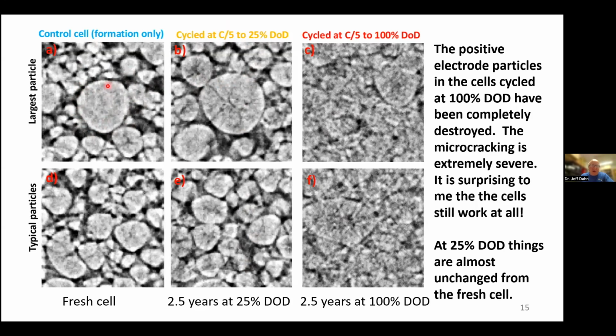We tried to find a large particle to compare. There might be some evidence of microcracking here, but very little. The image between the fresh cell and one cycled at 25% DOD for 2.5 years or 16,000 cycles are not very different. But if you look at the positive electrode in a cell that's cycled at 100% depth of discharge for 2.5 years continuously, and this was 3,000 charge discharge cycles, these particles have virtually disintegrated.